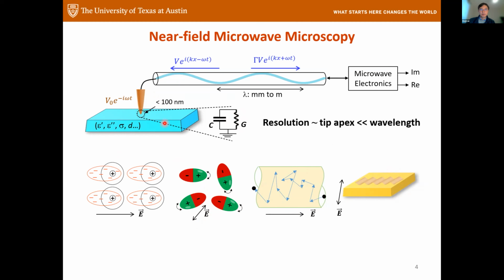Now, before I move on, let's say you have a 2D layer underneath a dielectric layer. This is a quasi-static simulation of how the field is distributing. One can easily understand this. Let's say the material is very insulating. So this is the potential, and you can just do the derivative or gradient in your mind, and you can see this is the electric field. Right? So the electric field easily goes through an insulating layer. But the electric field will stop at the conductive layer because the electrons will screen the electric field, so the electric field is very much concentrated underneath the tip if the material is very conductive. The 2D material is very conductive here.